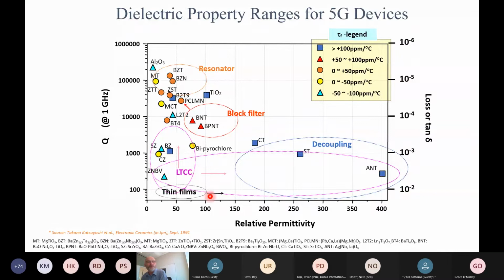Polymers would also be grouped in this category where we have low permittivity, somewhere in the 2 to 5 range, maybe 2 to 10 range. And then the Q values are somewhere between 100 and 1,000, depending on the frequency. This is normalized to about 1 gigahertz because these properties are also frequency dependent. And then at very high permittivities, there are applications for like decoupling capacitors and other sort of miniaturized devices, typically lower frequency in the maybe hundreds of megahertz range. And there we're dealing with a lot of titanates, for example. So that just gives you the trade-off.